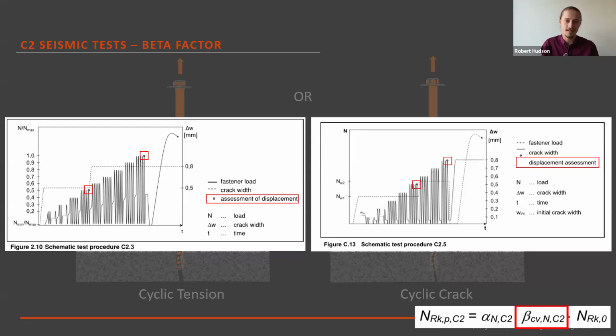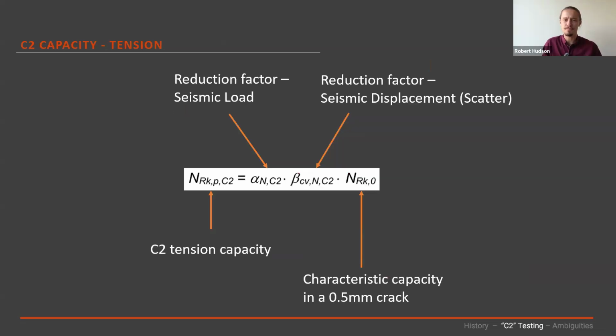And so if you have any anchor that is displacing unreasonably far in these test programs, it basically just doesn't allow it to get a C2 capacity. And these are pretty reasonable things. We don't want anchors to displace a huge amount when we're using them. We're not accounting for that in design. But the actual impact on the end result is reasonably minimal. It's more of a pass-fail kind of thing with regards to displacement performance. Basically, when it's all said and done, that's where this C2 capacity comes from.